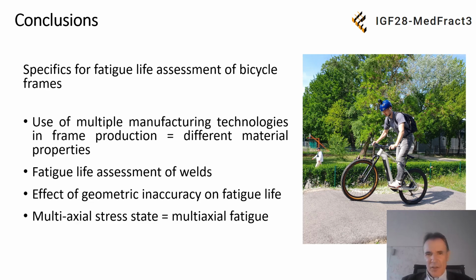The next specific is the effect of geometric inaccuracy on the fatigue life, which induces additional stresses, additional loading. In the majority of cases, this is additional torsion. This additional torsion creates additional shear stresses, which are necessary to consider in the process of fatigue lifetime assessment. These stresses are possible to measure directly in operation or directly on the bicycle frame on the stand. This additional torsion and shear stress lead to the last specific, the multiaxial stress state, which has many problems and is not standardized to this time: the selection of an appropriate hypothesis for multiaxial fatigue, and the right cycle counting method. This is all about the specifics present on bicycle frames.